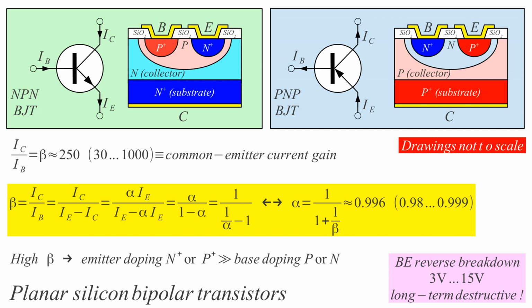Some additional details we should learn about bipolar transistors is that this strong doping of the emitter here calls for a very low base-to-emitter reverse breakdown. This reverse breakdown voltage is just between 3 volts and 15 volts. For transistors for very high frequencies, maybe even less than 3 volts. 15 volts for very low frequency, maybe high power transistors. But this breakdown, if it is used on the long term, it is destructive. It destroys this junction here.